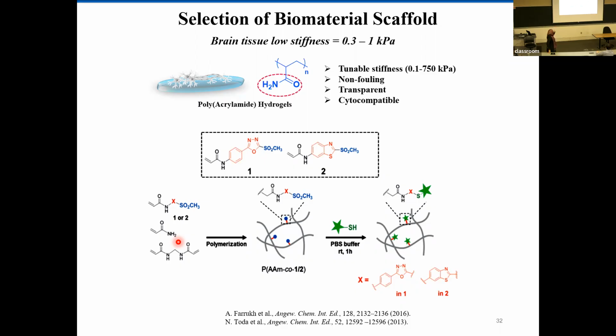The brain itself has a very low stiffness, between 0.3 and 1 kilopascal. So what we decided to use is polyacrylamide, because we can tune the stiffness, and it's very cheap and very easy to make. But there is a problem with polyacrylamide gels, this amide group. The amide group is not very reactive, which means that you cannot covalently functionalize anything on these gels. We can do some coating, but it's not very helpful.